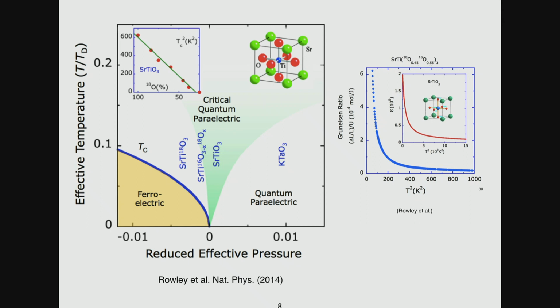And so what's been done experimentally is one can actually drive it ferroelectric and then apply pressure, either external or chemical pressure, and what's been found is that it actually has a quantum critical point here, okay? And for example, it has a diverging dielectric susceptibility, and this is a special mixture of O16 and O18. And it also has a diverging Grüneisen parameter to indicate that it really is a quantum critical point.